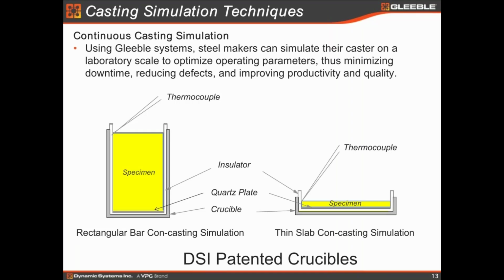flat sample casting, because slab or thin strip casting, it's all rectangular. So we have developed a crucible that is very simple, just a metal screen, and you put pieces of insulators at the bottom, and you put a quartz plate. So you can put a thermocouple at the edge, and then heat it to whatever temperature you want to get it fully melted, and then you control solidification.